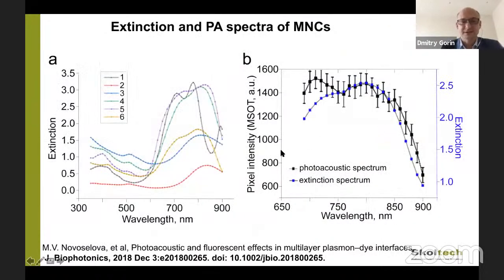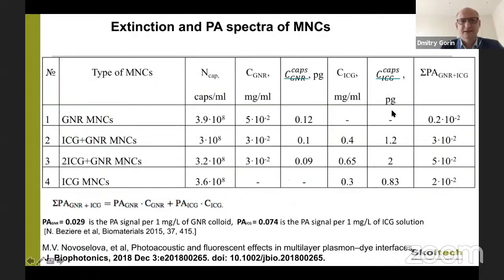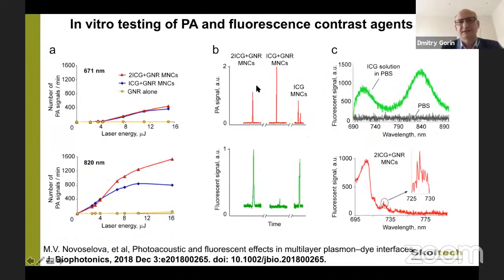And here you can see extinction spectra, and we have broad absorption of our particles in the transparent window of biological tissue, and we have good correlation between optoacoustic signal and extinction spectra. And as a result, we can calculate the expected photoacoustic signal, and you see the maximum photoacoustic signal. Our expectation was that it should be the structure with ICG encapsulated with albumin and ICG in the shell together with gold nanorods. But in reality, we obtained the maximum signal for the structure that has ICG only in the shell, and it's a very interesting result.